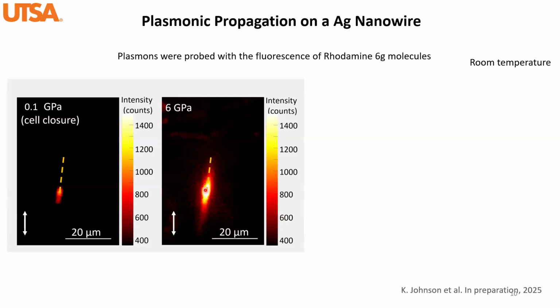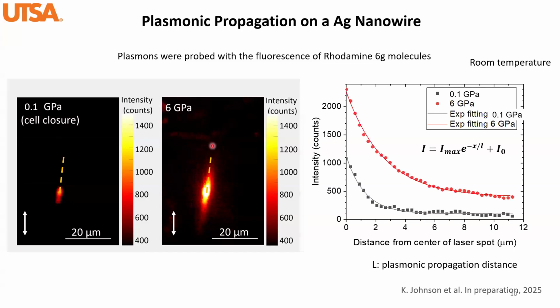So we did a cross-section profile along the nanowire to tell us the intensity as a function of the distance from the center of this laser spot. This figure plots the intensity profile. I would stress here that we don't really care about the intensity, because we had to adjust the intensity as we increase the pressure, since the fluorescence of the dye gets quenched a lot by the high pressure.